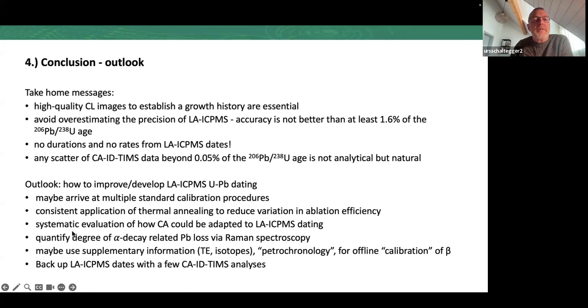And we should undertake more efforts to systematically evaluate how chemical abrasion could be adapted to laser ablation dating. It cannot just be used in the same way as we use it for ID-TIMS, because when we chemically abrade the zircons, they are very fragile afterwards. We have to put them into an epoxy mount afterwards and polish them. So this is a nightmare from the manipulation, but maybe there is a way to adapt it.